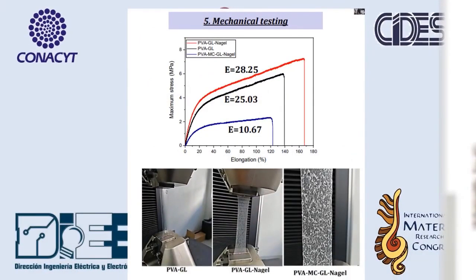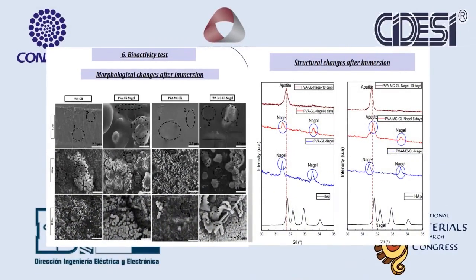Mechanical tests showed that the PVA membranes with glycerol with and without NAGEL particles have very good mechanical properties, especially elongation above 100%, which is good for wound dressing as they are flexible and can be adapted to different wound areas. The bioactivity test shows that the membranes are able to promote the biomineralization mechanisms.